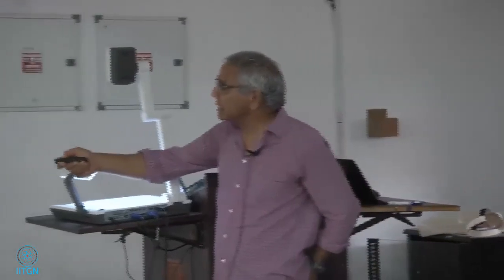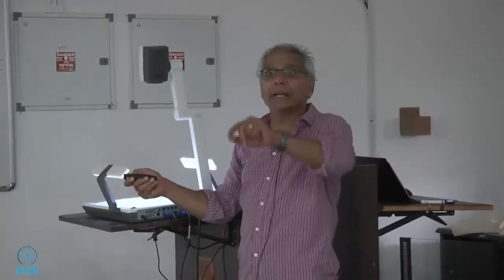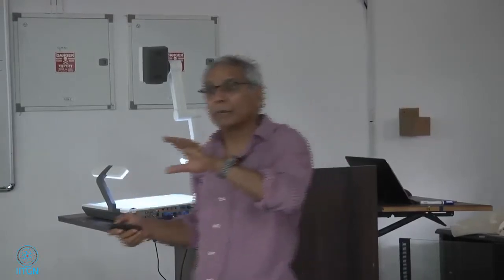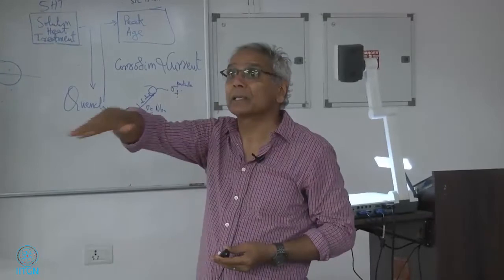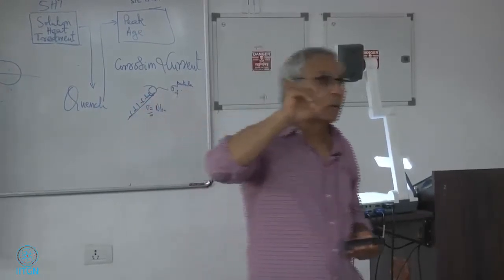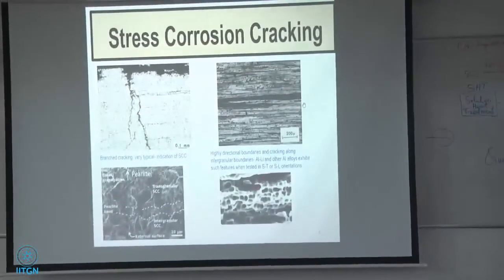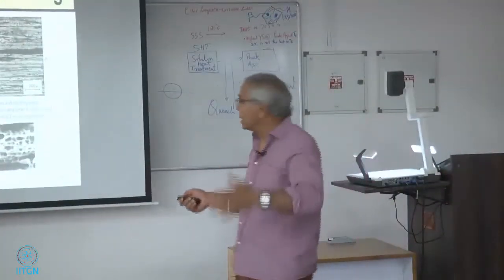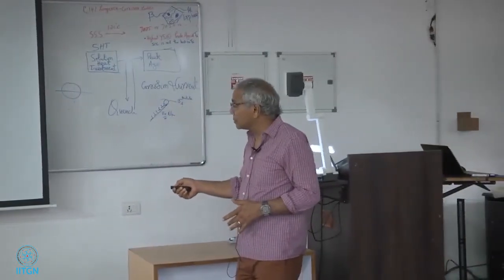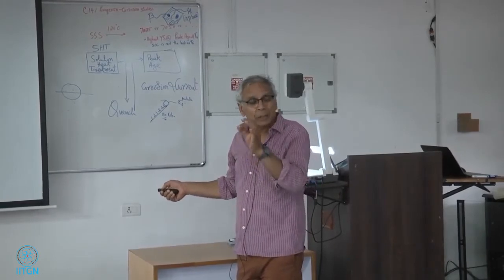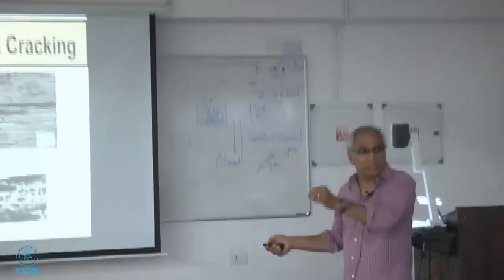So this is an interesting fracture surface of an overaged aluminum alloy. Remember what we said: in the overaged condition, in a precipitation hardened alloy, we have precipitates on the grain boundaries. So when it fractures, you see these voids on the grain boundary. This is a grain boundary actually. You can only tell if you're doing many of these. I cannot tell if it's an intergranular fracture or not, but if you do many of these, eventually you'll find out, oh, this is a grain boundary, and these are coming from the grain boundary particles. Okay? So this is intergranular microvoid coalescence, IGMVC.